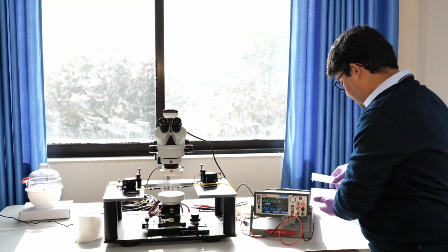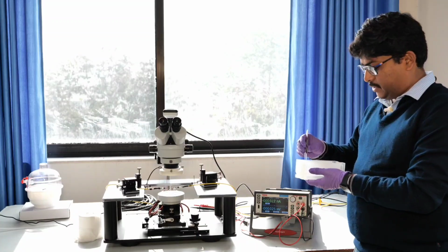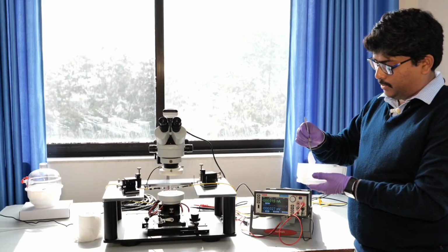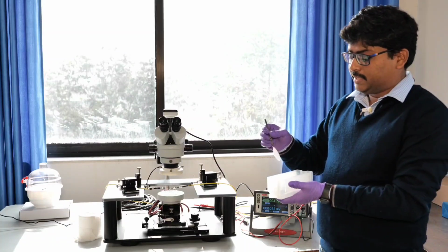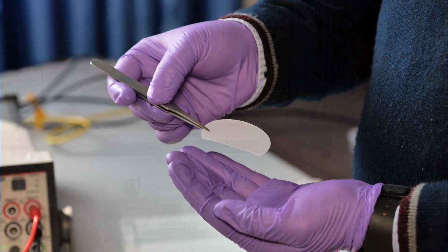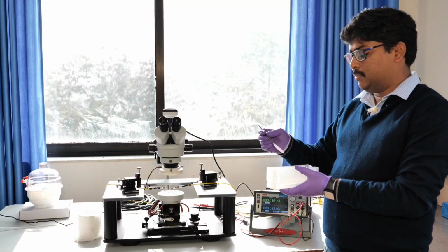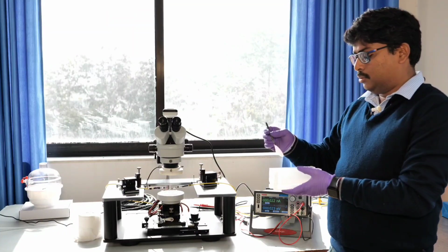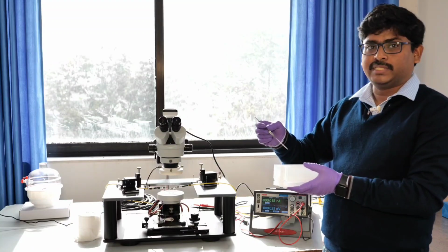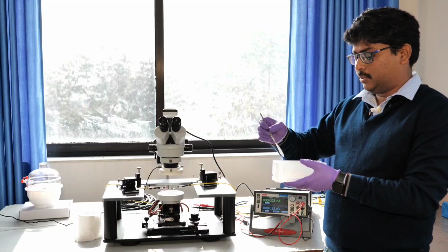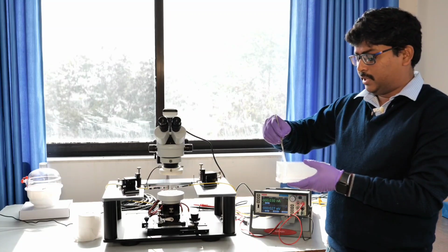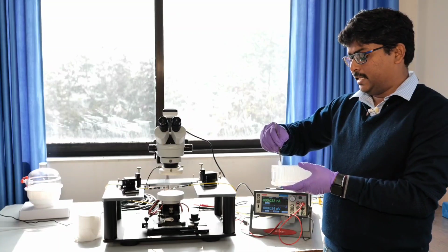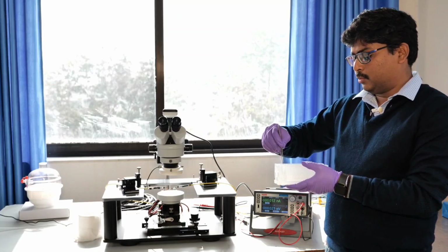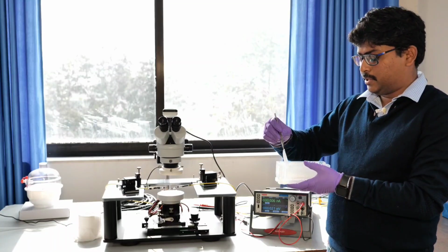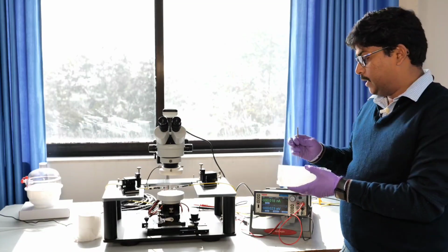We used this kind of transparent sapphire substrate to develop this material. This is again a 2-inch sapphire substrate. Although, as I mentioned, the growth system or material development system was completely customized, so we had to use a small portion of this substrate. We could not use this entire 2-inch substrate to develop this material. So after developing this Sn-doped gallium oxide good crystal quality thin film on this type of substrate, we fabricated 2-terminal devices,